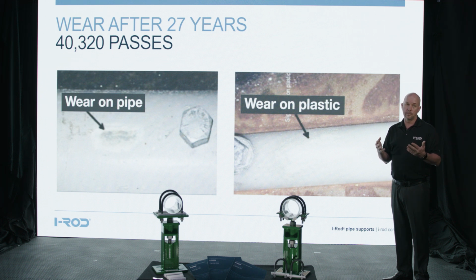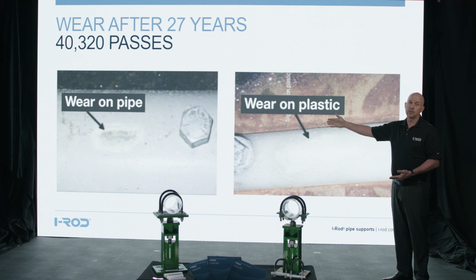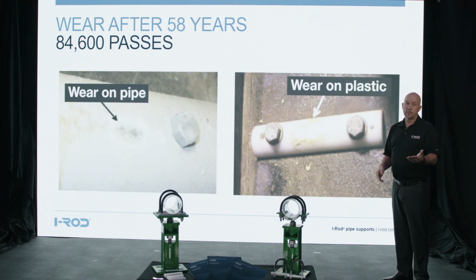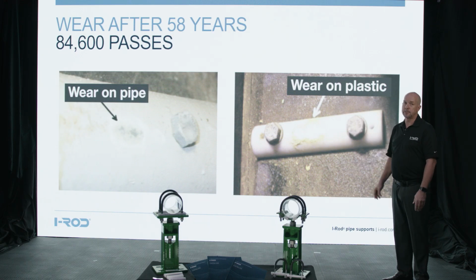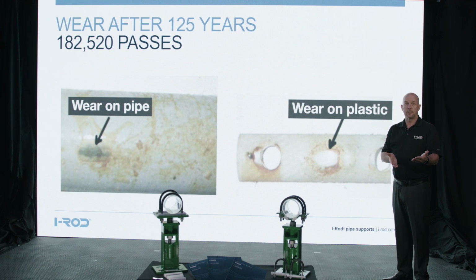If you assume 4 movements of a pipe per day, it would take 27 years for the pipe to move 40,320 times, or 27 years to wear through the first layer of a 3-part epoxy coating. Following that same logic of 4 movements per day, it would take 58 years to wear through the second layer of the epoxy coating and expose the primer. You'll notice there's very little damage to the I-rod at this point. Following the same logic, it would take 125 years to wear through all 3 layers of the coating and actually expose the steel. Again, very little damage to the I-rod. So, thank you very much to the company who paid for this test for us. We did not know that I-rod was such a great wear-resistant material, but now we do, and we can promote and sell it as a wear-resistant material.